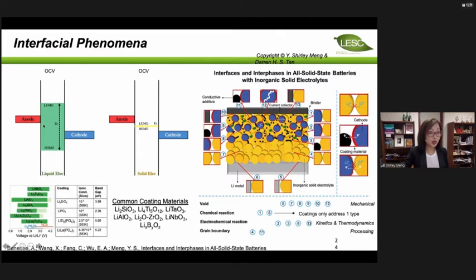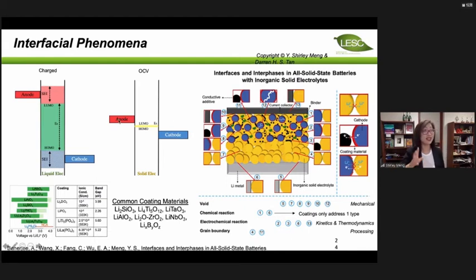So the difference between liquid and solid is that in the liquid electrolyte, I have intercalation materials like graphite and transition metal oxide. They are stable within the HOMO-LUMO level of the liquid electrolyte. When I cycle the cell, of course, there's SEI. Now, in the solid state, we have big trouble because the anode is lithium metal. We want to enable lithium metal, right? And I just told you, lithium metal reacts with everything, and that includes many of the polymers and sulfides.